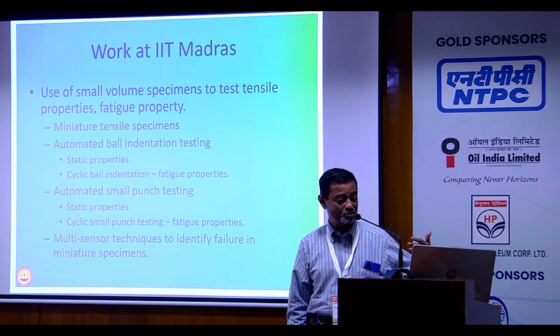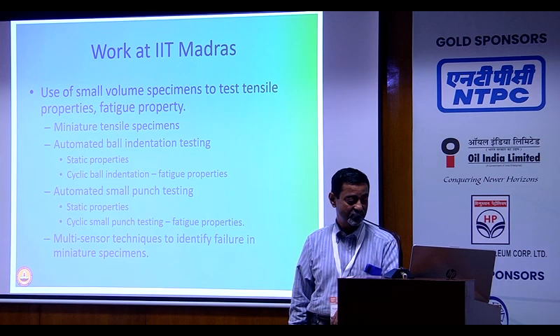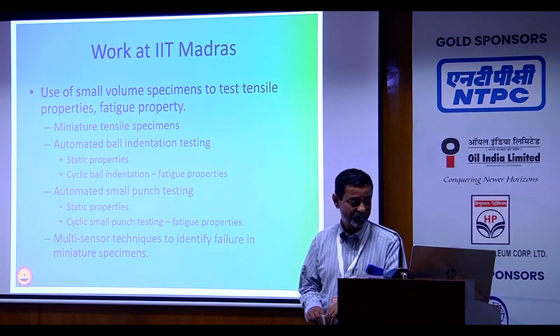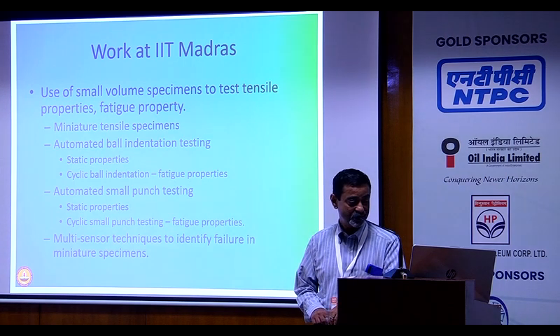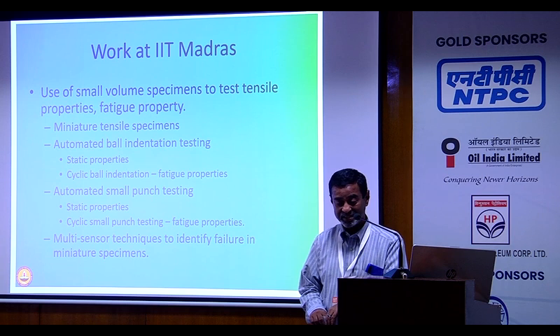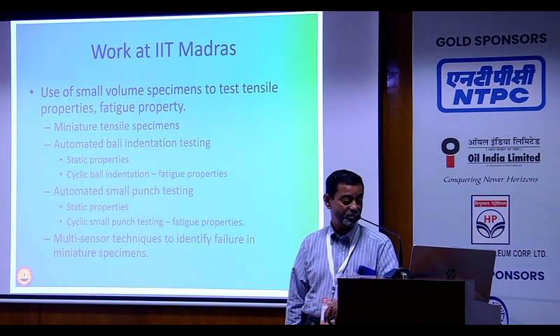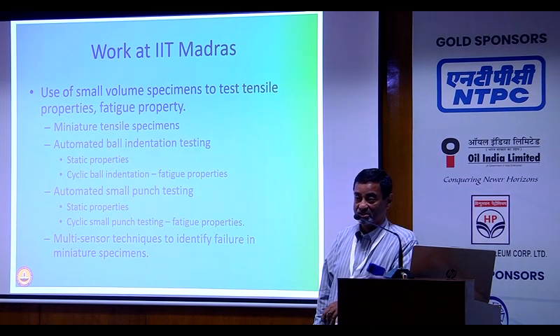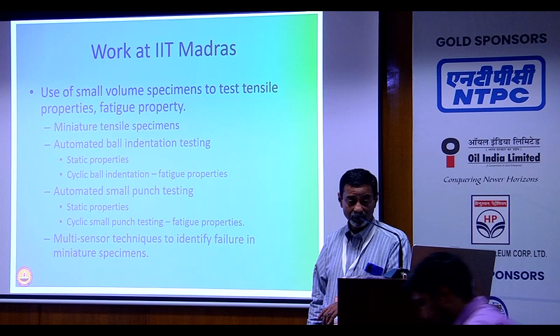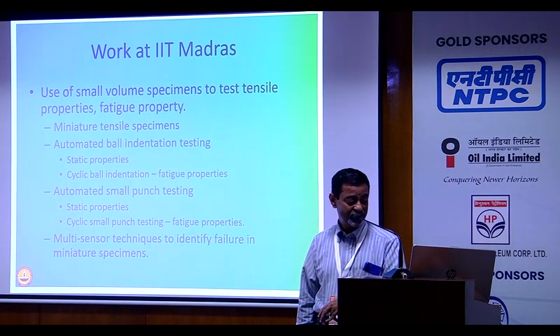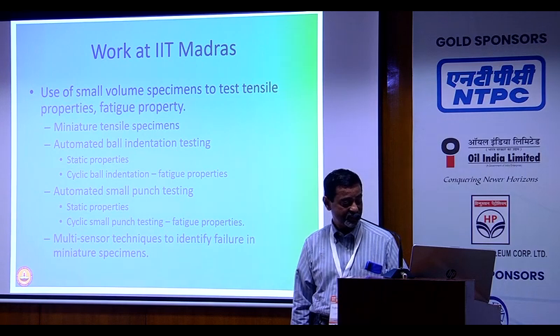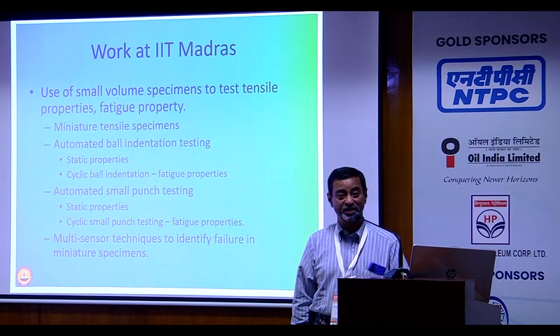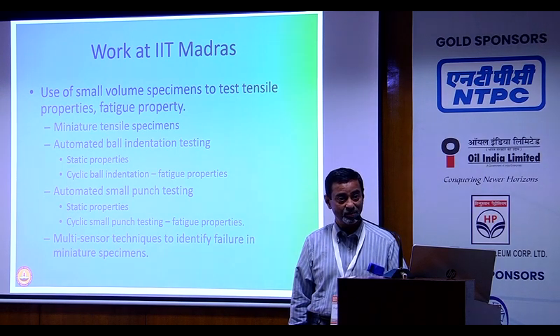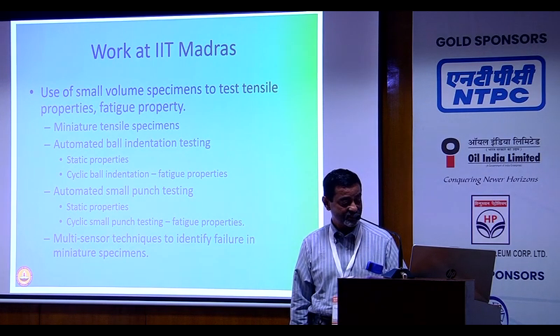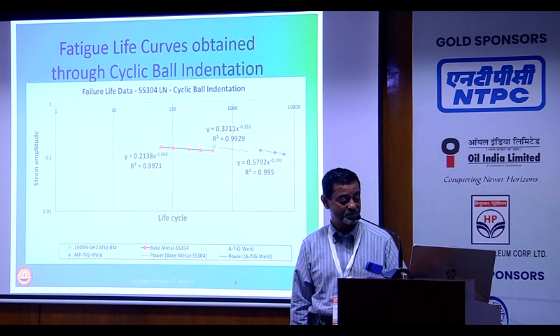And I don't want to get into too much detail. I'll just show you a few of the results. But what we did over the last 15 or 20 years is to work on small volume specimens to test the tensile properties and the fatigue properties. We looked at miniature tensile samples. Then we used the indirect method called ball indentation testing, both for static indentation and fatigue properties. We did small punch testing, because the state of stress changes depending on the test method. You will have a uniaxial or a biaxial or a triaxial state of stress. So this is all that we did, and then we did multi-sensor techniques to identify failure in miniature specimens.